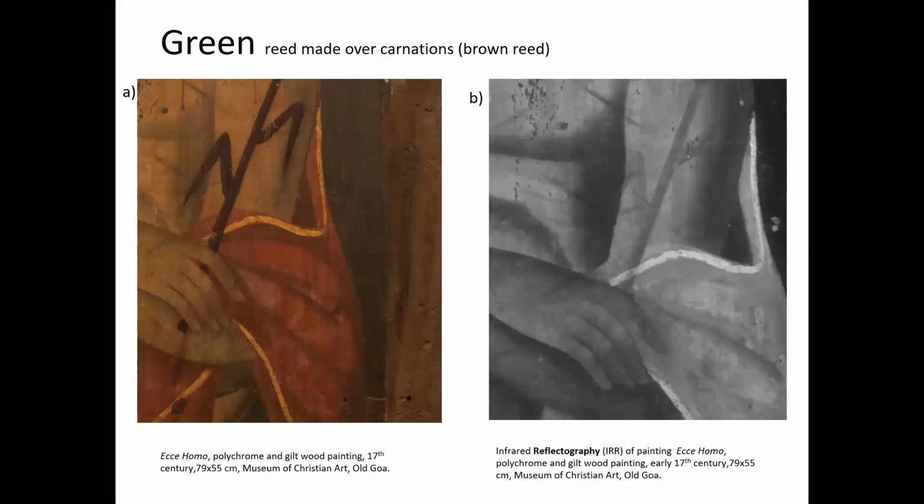In this technique, the difficulty concerns high fluorescence background, and the fact that also verdigris is chemically unstable, reacting to oxygen and light, and originates this discoloration, turning to brown over the years.